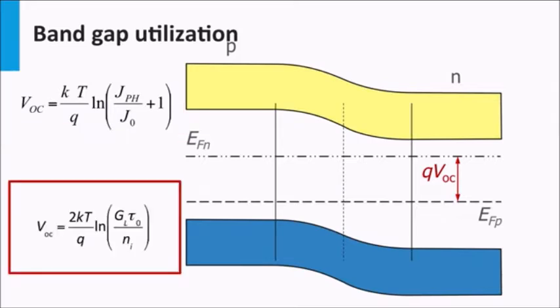This equation can be expressed in terms of the generation rate G, lifetime tau of the minority charge carriers, and the intrinsic density of the charge carriers of the semiconductor material. As the derivation of this equation is out of the scope of this lecture, we have included it as an exercise in this week's homework. The equation tells us 2 important aspects of the open circuit voltage. If we increase the irradiance, or in other words, the generation rate of charge carriers, the open circuit voltage is increased. This is a welcome effect which is utilized in concentrator photovoltaics, which we will discuss later this course.